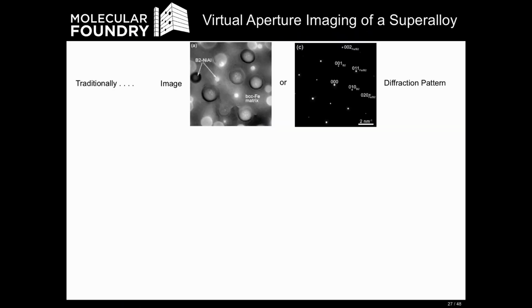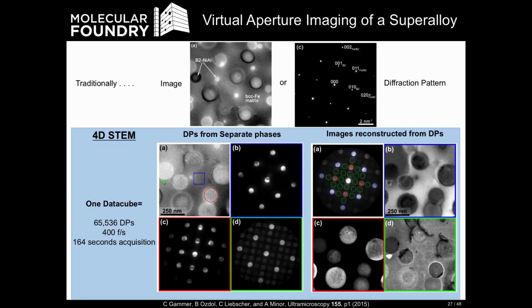So this is an alloy. It's a BCC Fe matrix with some precipitates. You can see there's a couple different precipitate compositions, but they're all epitaxial. They all form conventional cubic or square diffraction patterns aligned along this 001 zone axis. At the top, I've shown the traditional images. You can get a real space image or a diffraction pattern of this sample, but interpreting what all the contrast means in the image is not trivial. Often you have to do selected area diffraction, where you place an aperture over the matrix, or over the precipitate, or over the shell of the precipitate, in order to solve exactly what structure it is. But from one 4D-STEM data cube, where we recorded about 65,000 diffraction images, we can pull out a lot more information.